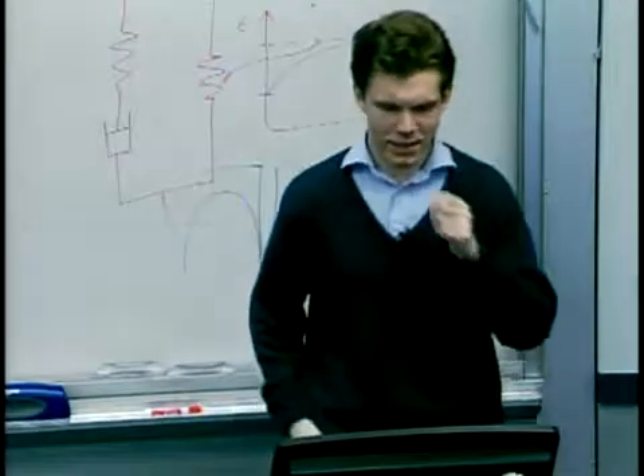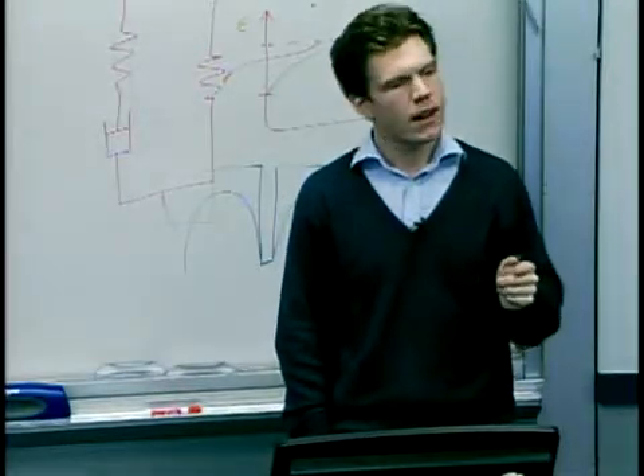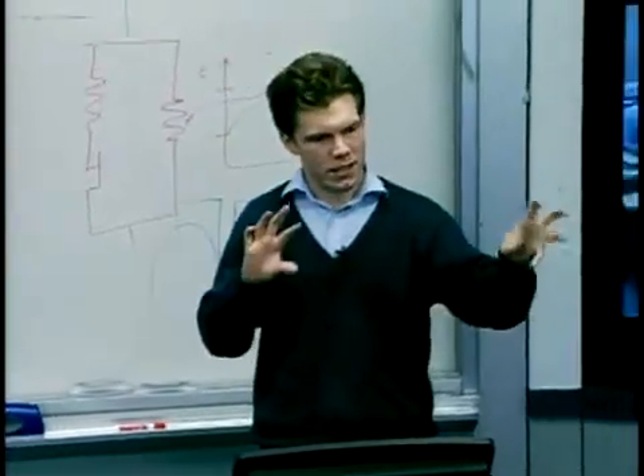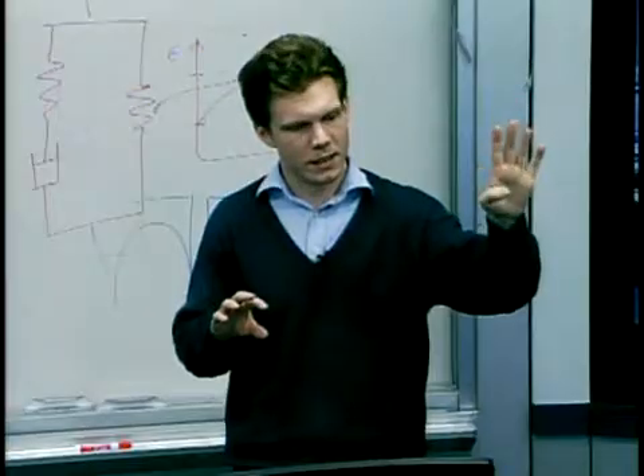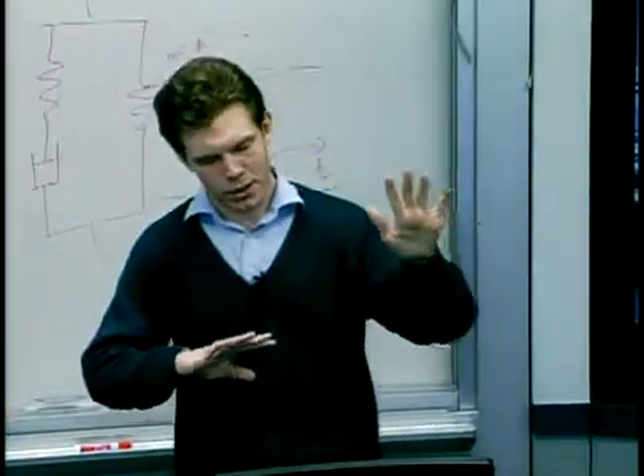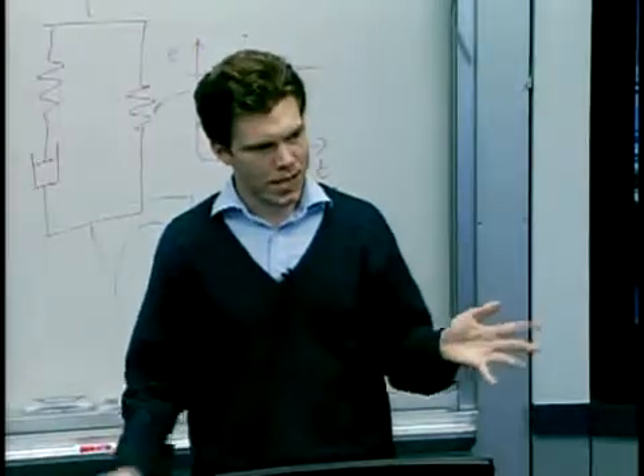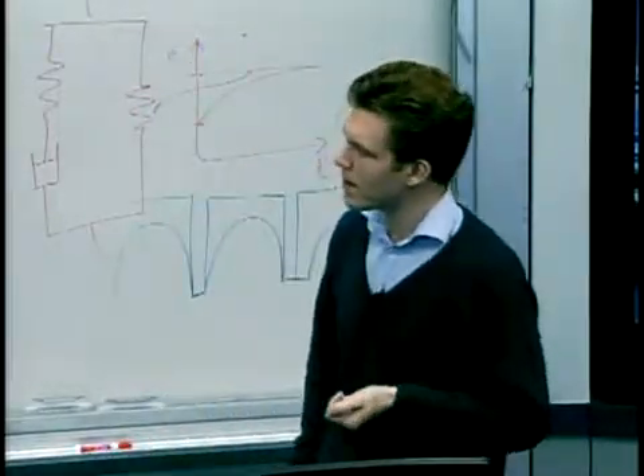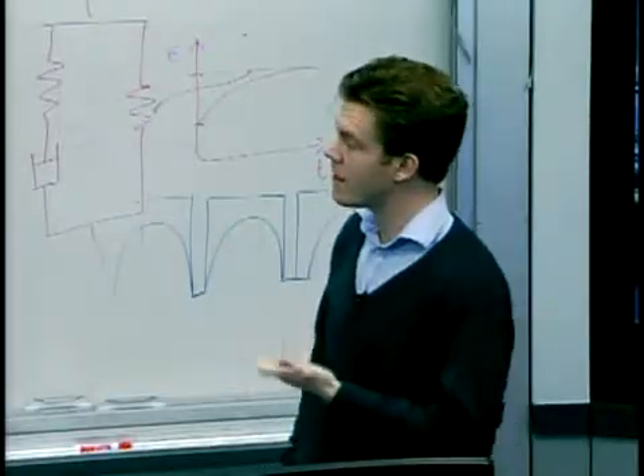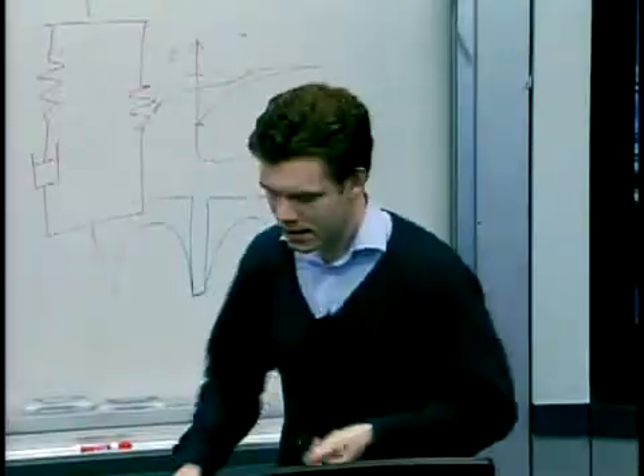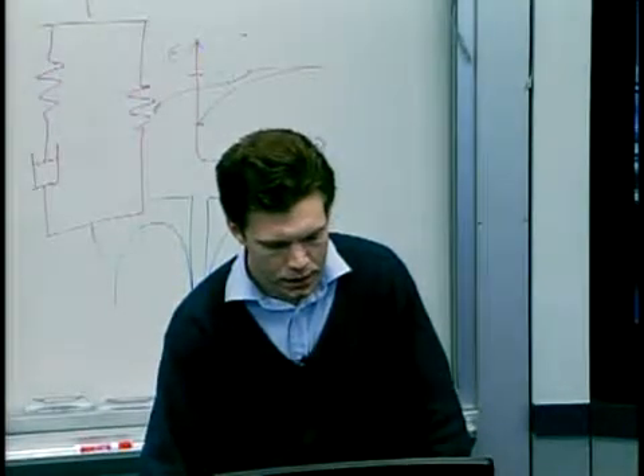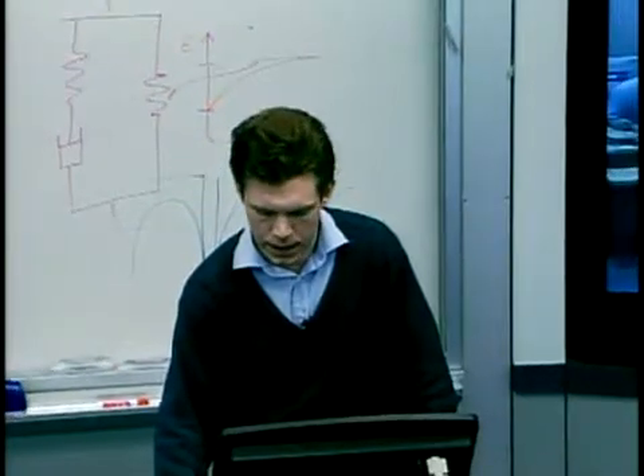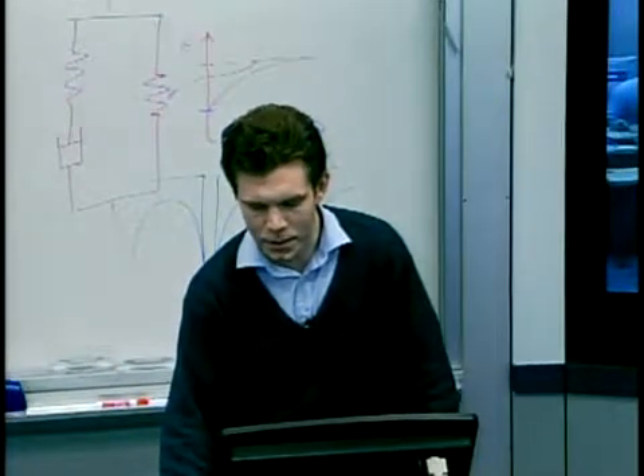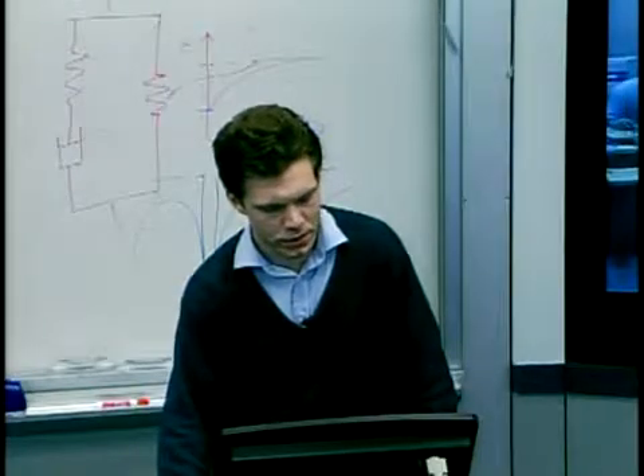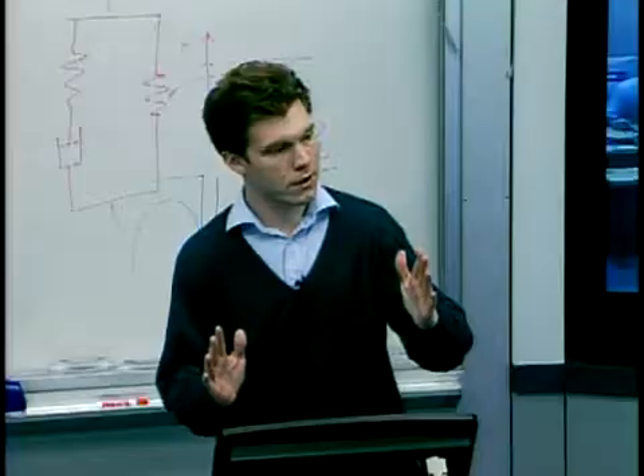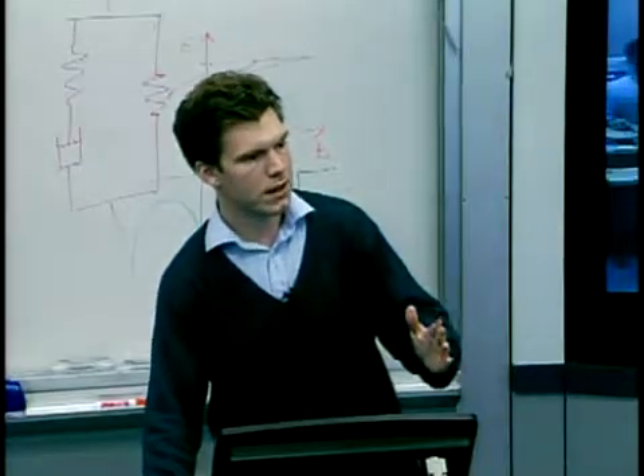Now, there's one really interesting thing about these results, and I mentioned that I had 2 sets of each feature size, and one was oriented vertically on the stamp and one horizontally. And I just put those on there on the off chance that there was anisotropy in the materials. And it turns out that with this Topas sample, which is a gift from the supplier, there is really strong anisotropy. And so you can see that the filled in symbols are for an arbitrarily defined orientation of 90 degrees, and the open symbols for 0 degrees. So turning the feature through 90 degrees gives you this really big difference in penetration.